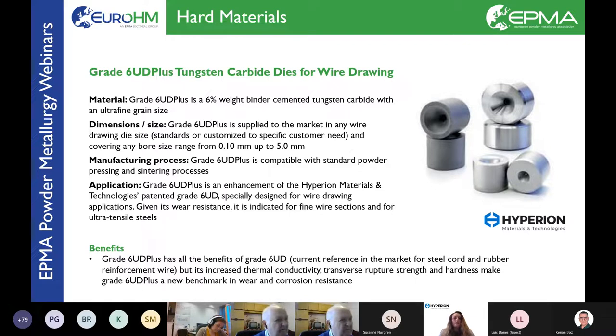During the wire drawing process, many steps are needed. At the beginning of the drawing line, or dry wire drawing, drawing speeds are slower, wire diameter reduction is high for each step, and the material used for the drawing nibs is required to exhibit high fracture toughness. On the other hand, towards the end of the drawing line, or wet wire drawing, drawing speeds are faster, wire diameter reduction is low for each step, and the material used for the drawing nib is required to exhibit high hardness, thermal conductivity, and wear resistance.